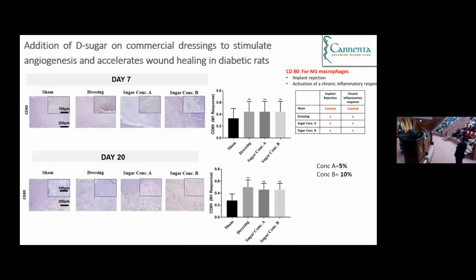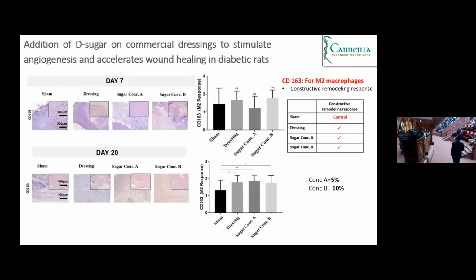For implant rejection and activation of a chronic inflammatory response, we use this CD80 basically, and there was no bad news from any of these materials on day 7 and day 20. And similarly, we stained these materials with CD163, which is for the constructive remodeling response. And we have seen that the dressing, which is alginate, and also 5 and 10%, were helping in constructive remodeling as well.